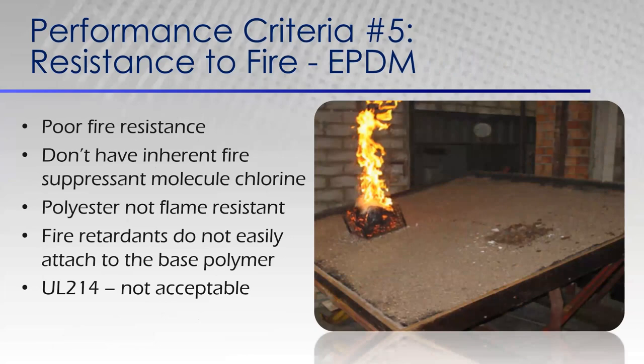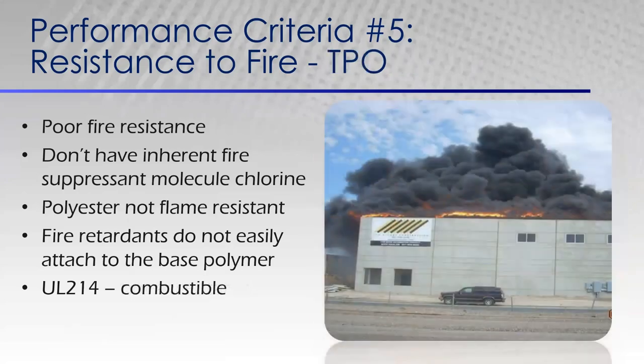When we look at EPDM, it has a very poor resistance to fire because it doesn't have the inherent molecule, chlorine, to suppress the fire. The polyester scrim is not flame resistant, and fire retardants don't attach well to the EPDM. So based on UL 214, when the fire is removed, it is not acceptable and is considered combustible. When we look at TPO, as I mentioned earlier, it's UV exposure or fire resistance, one or the other; you can't get both with the TPO. It does not have that inherent suppressant molecule, chlorine, present in its makeup. Its polyester scrim is also not fire retardant, and those fire retardants don't easily attach to the base polymer of TPO. So based on UL 214, it is considered a combustible product and therefore has poor fire resistance.